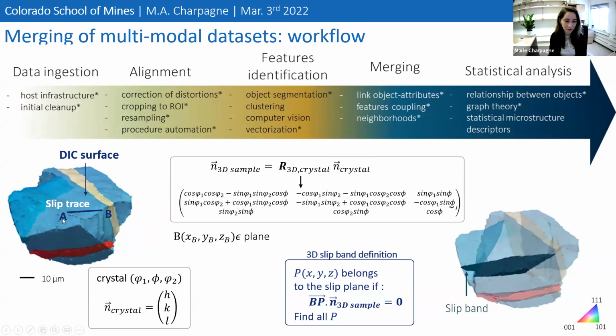So the framework that I developed takes the slip trace and determines the {111} plane on which every single slip band is lying, for over 1,000 slip bands in the data set. We find automatically which one of the four {111} planes is active for each slip trace. Since you know that, and you know your local crystallographic orientation, you can rotate back this slip plane and represent where it would have landed in the grain. It's essentially calculating the normal of that plane in three dimensions. Given that we have at least two points, here the endpoints of the slip band, a normal to a plane plus one point fully defines the plane. That's how we reconstructed every single slip band in this data set.